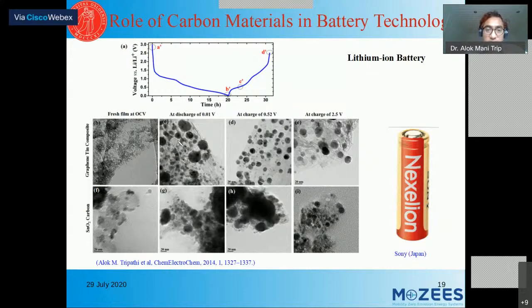So we can see over here at point B, the particle size, which is in nanometers, has increased into the hundreds of nanometers. And when we start removing lithium, the particle shrinks. But you see the distribution is very good on this surface. And when we completely remove the lithium, we still have a very good particle.